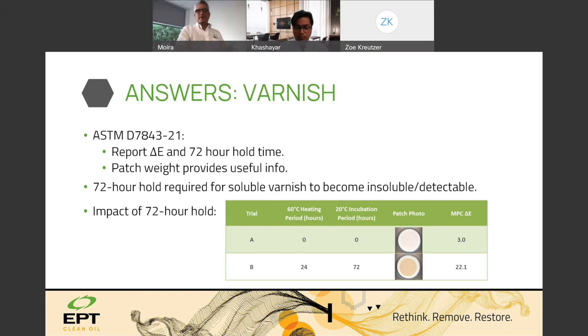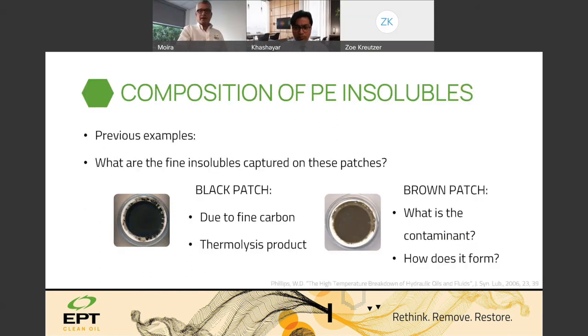Which demonstrates the point. If you see black on your patch, that's because of high temperature breakdown, not chemistry breakdown. So when you see brown patches, that's reflective of chemistry breakdown and varnish tendency. Whereas when you see black, the oil is being exposed to extreme temperature breakdown and is generating carbon.